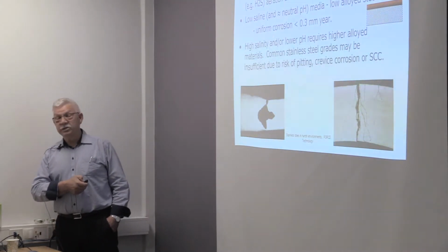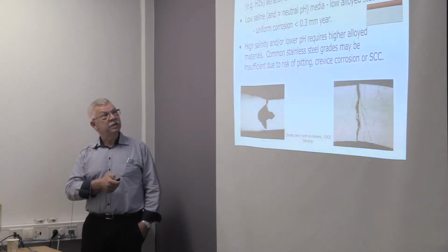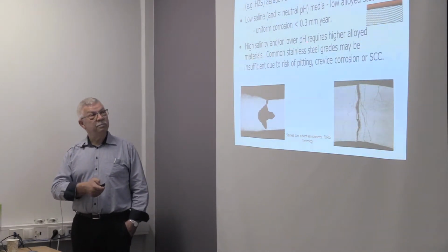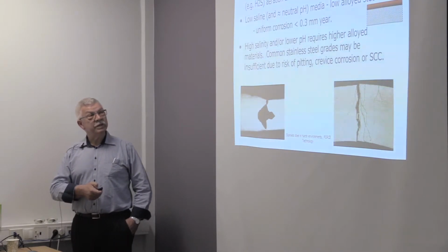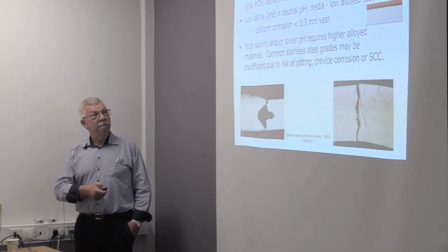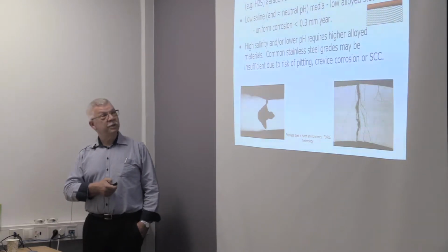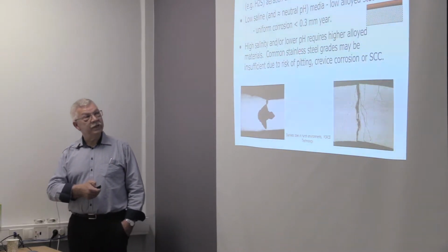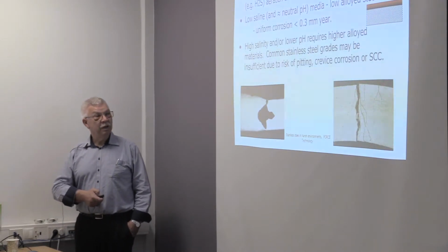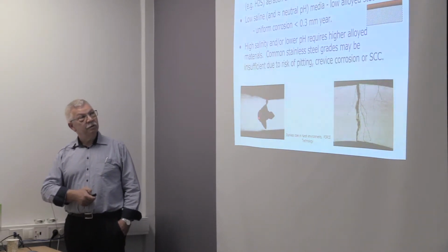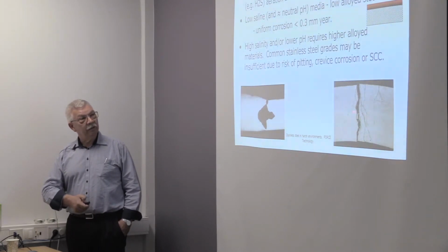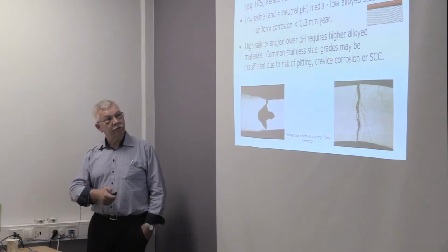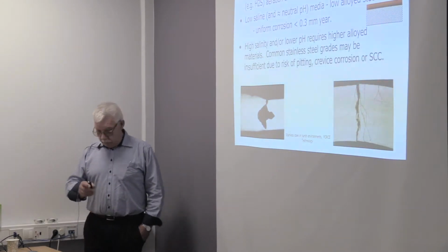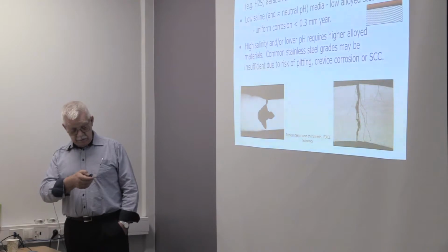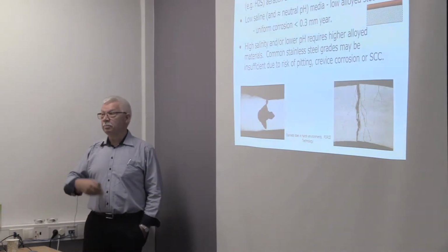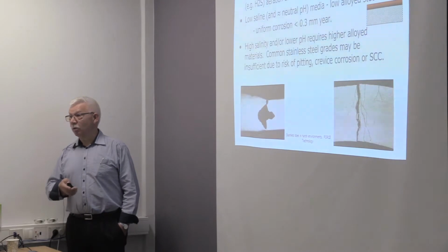But if the salinity, the amount of salt, is increased, and pH might be lower, then we must have higher alloy materials. And like some of the media that we have just discussed, common stainless steel might not be enough. We might risk pitting from the chlorides. We might have stress corrosion cracking. We might have crevice corrosion. So usually, if we have high salinity, then you have to go above ordinary stainless steel.